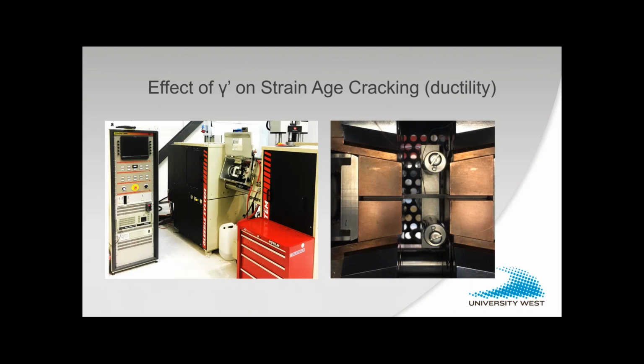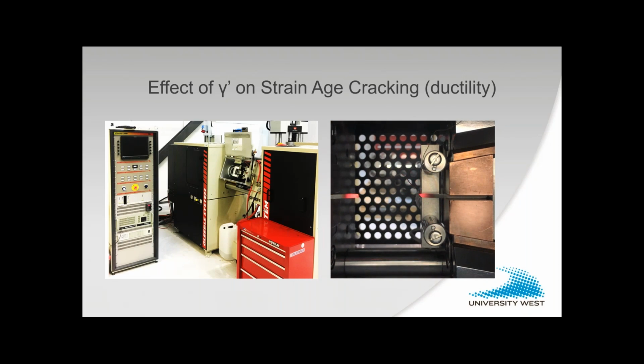So Fabian Hanning, he developed a new test where we decided to, I have a video here that I will show you. And basically, we have the sample, and instead of a slow heating rate, we heat up in a very fast manner, and then after a certain exposure time or dwell time, we pull past the fracture. So by doing this, we could vary not only the exposure time, but also the dwell time or the test time, and to systematically investigate what happens as we change test temperature as well as exposure time